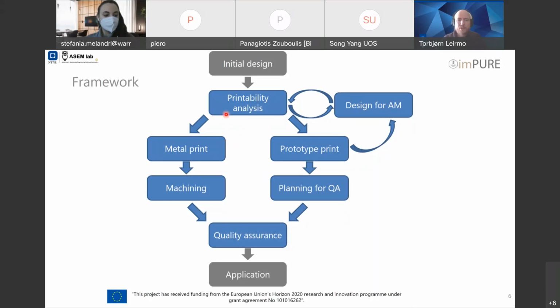But anyways, we propose that you should do this prototype because the metal print in powder bed fusion is quite extensive. It takes a long time. We're talking about print times from 4 to 5 days at the best for one of these molds that we've created so far. So with the prototype, doing this with polymers, you can cut this time in half, which means that you are able to do the planning for quality assurance much faster. In our case, we are using a coordinate measuring machine in order to qualify the parts to be sure that everything is on point before we ship them. And then we can program the machine using one of the prototypes before we actually get the final metal part.